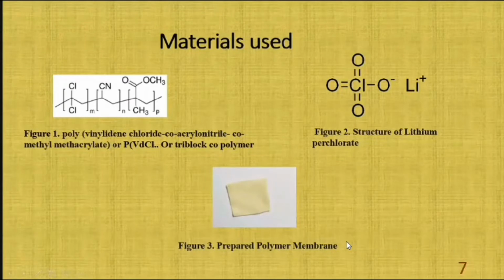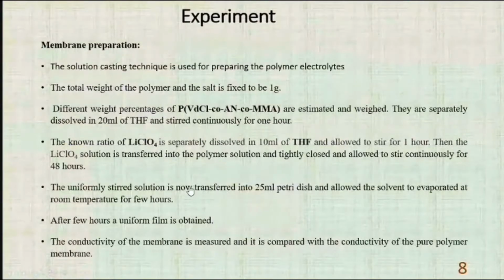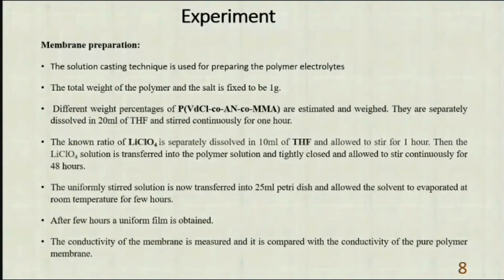Here the ionic membrane is used. The lithium perchlorate is the salt I have chosen to dope the material. Here we are using the solution casting technique to prepare the polymer electrolytes. We have used THF as the solvent and PVDCl as the polymer membrane. Since the pure polymer membrane is non-conductive, we dope it with the lithium salt.